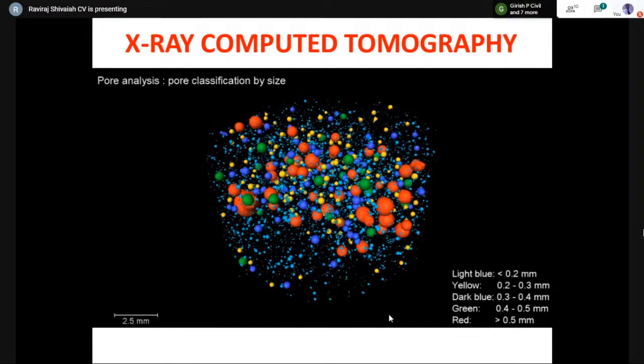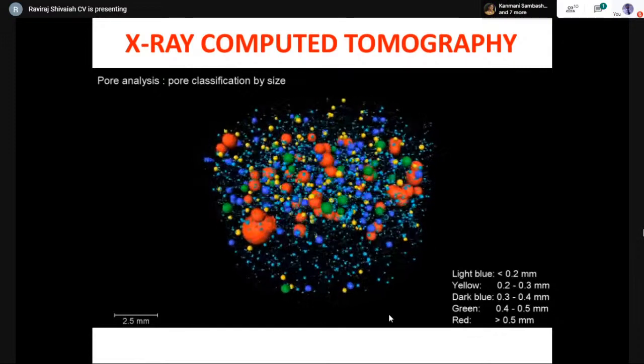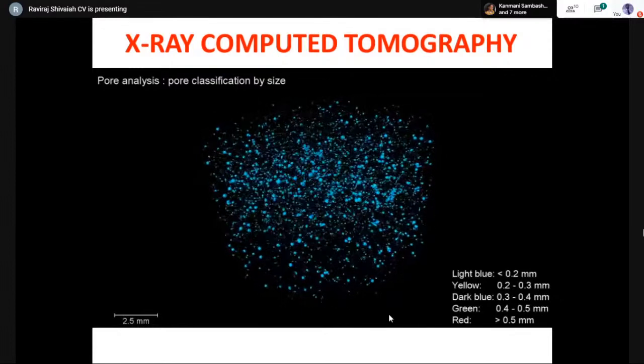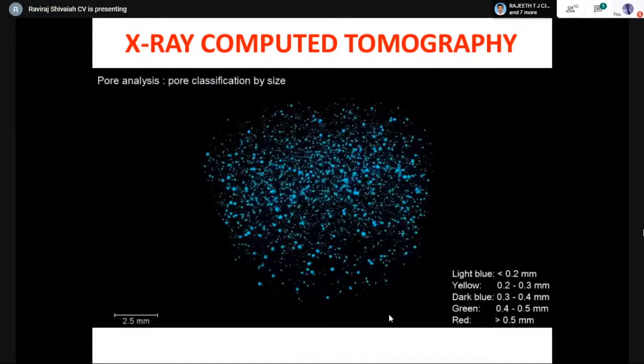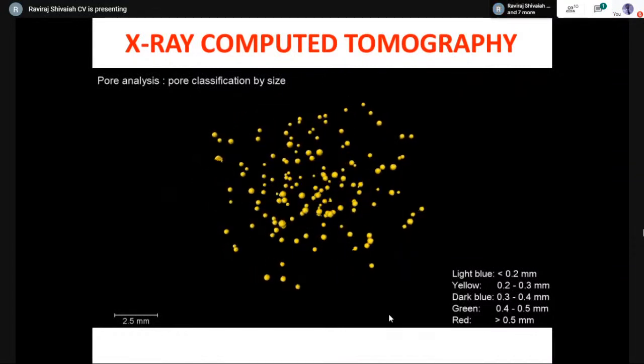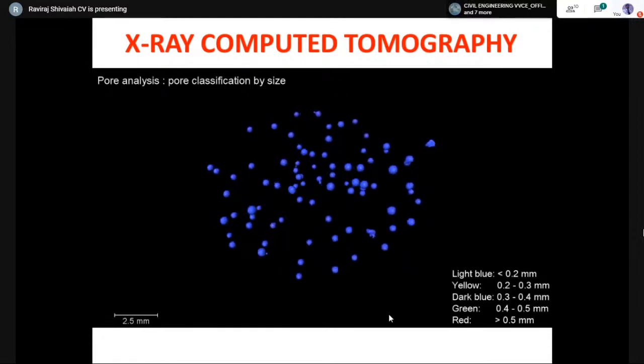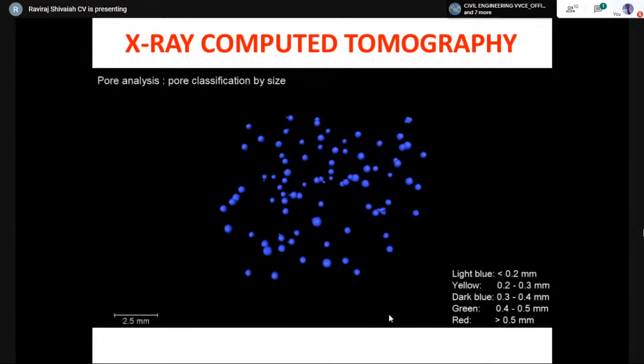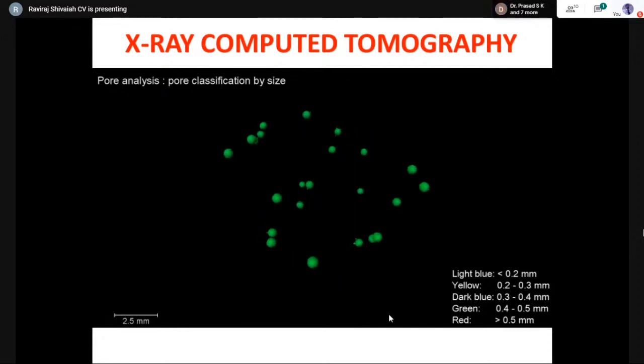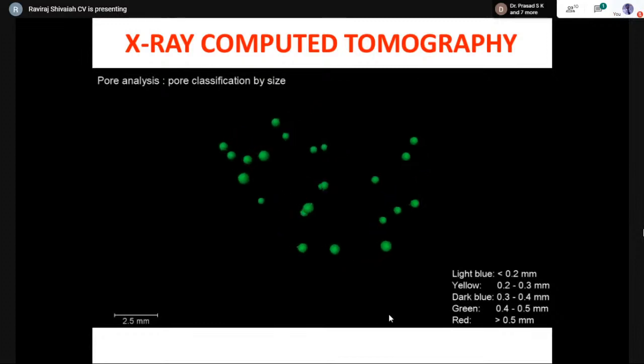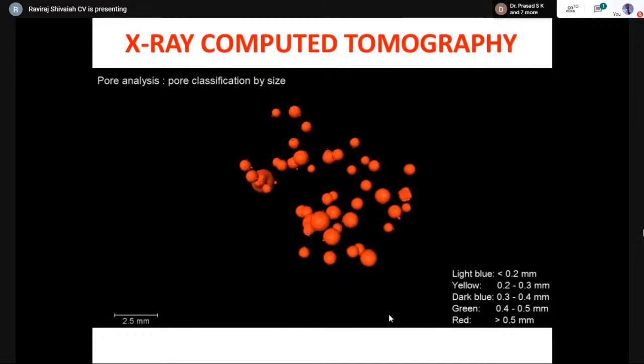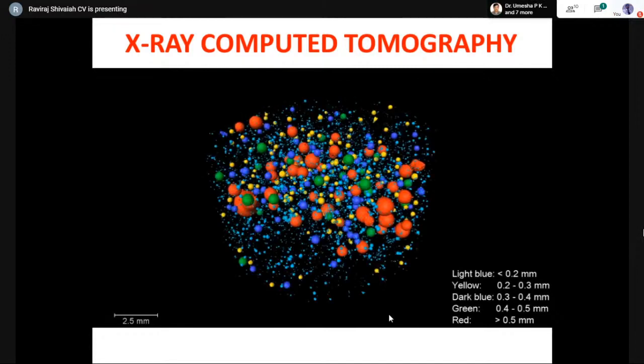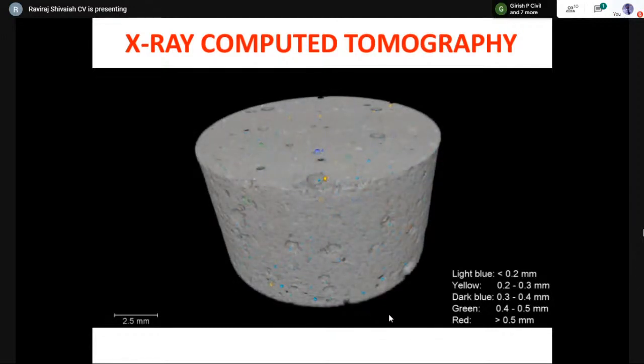Like small pores, medium pores, and big pores with different colors, like the light blue one, less than 0.2 millimeters, yellow colored pores, the one that you're seeing now, ranging from 0.2 to 0.3 millimeters, dark blue colored pores, ranging from 0.3 to 0.4 millimeters, and the green pores that we have here, somewhere between 0.4 to 0.5 mm, and more than 0.5 mm, red pores. So you can also do these kinds of classifications comfortably, and then know the anomalies. So what I'm trying to say is you can take these pores that you normally take out from your concrete surface, and then we can use this for any kind of testing.